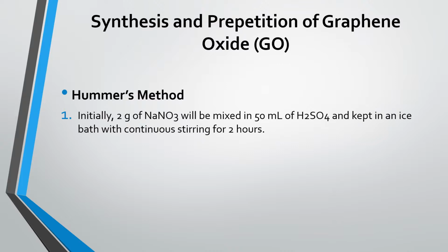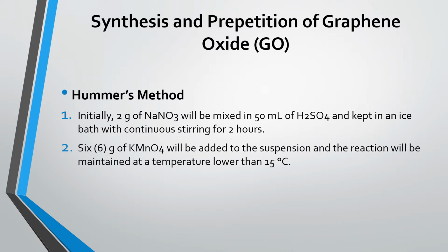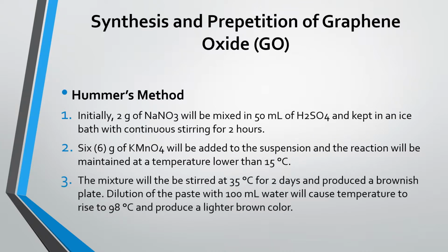6 grams of potassium permanganate will be added to the suspension and the reaction will be maintained at a temperature lower than 15 degrees Celsius. The mixture will then be stirred at 35 degrees Celsius for 2 days and produce a brownish paste. Dilution of the paste with 100 ml water will cause the temperature to rise to 98 degrees Celsius and produce a lighter brown color. 200 ml of water will be added.